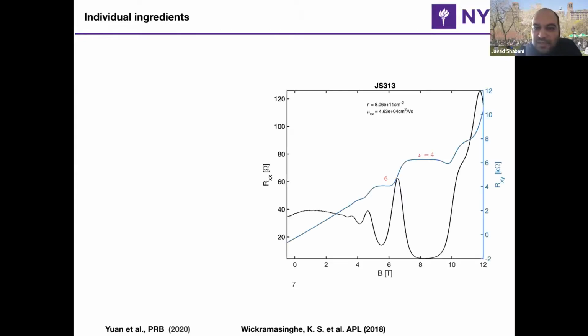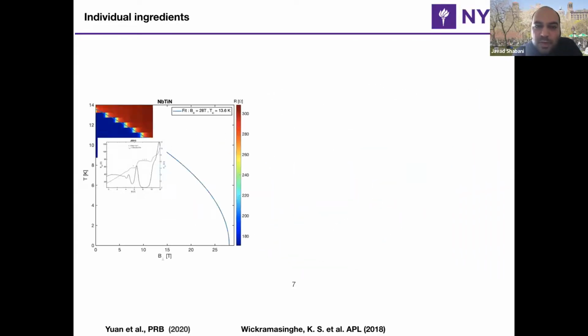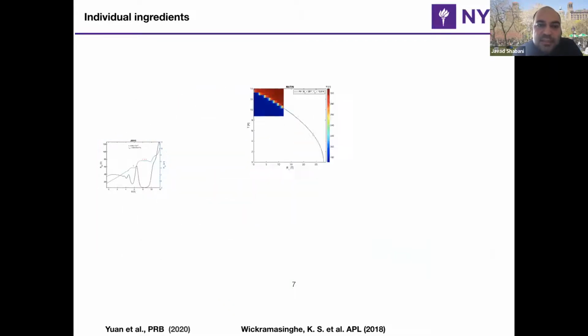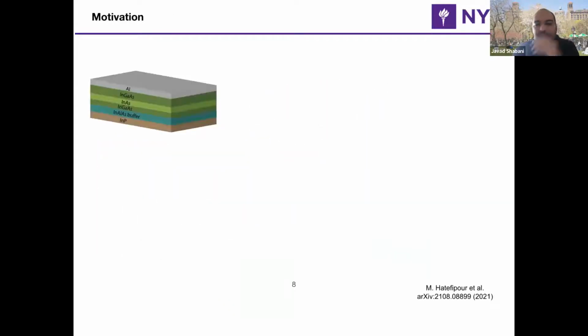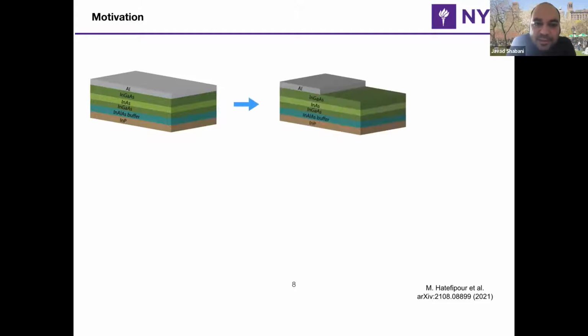For quantum Hall effect, obviously that's a different game, right? You want quantum Hall, but you also want something that supports superconductivity. And in this case, we need to go to niobium titanium nitride structures, right? So let me tell you how we make this. We start with aluminum on indium gallium arsenide. That interface is very pristine. We go ahead and expose part of this InGaAs to make our Hall bar.